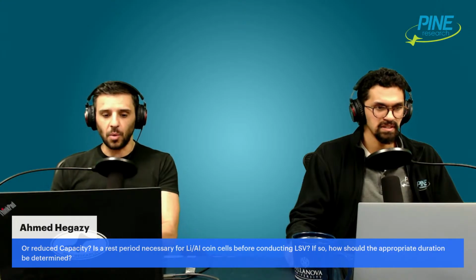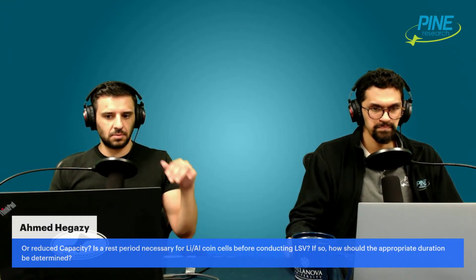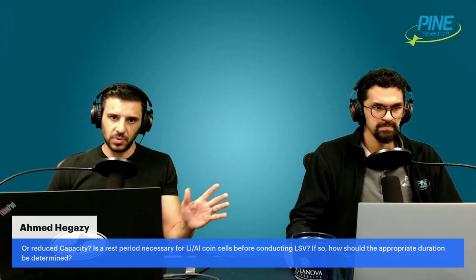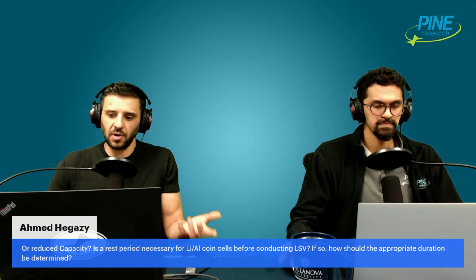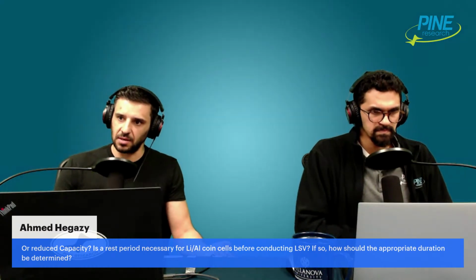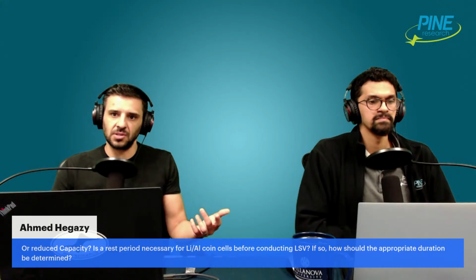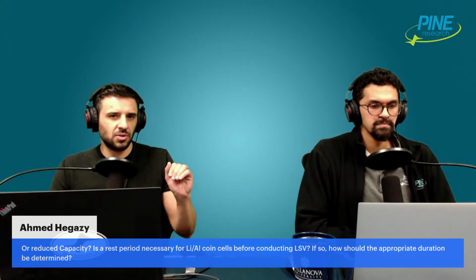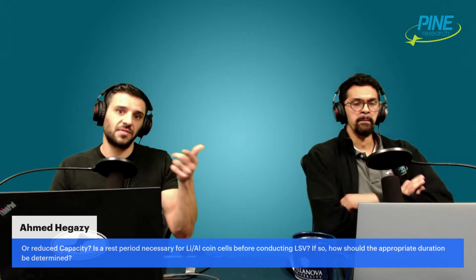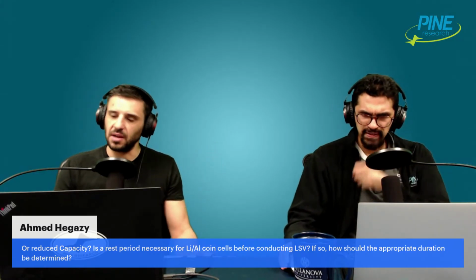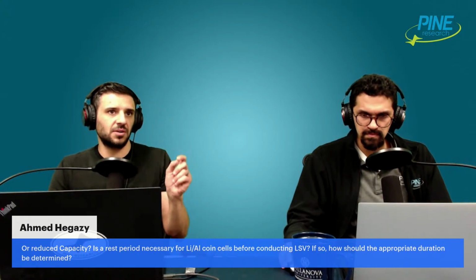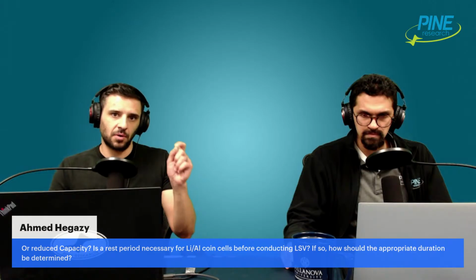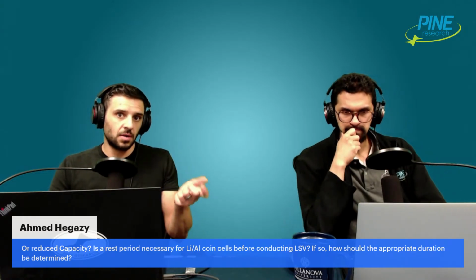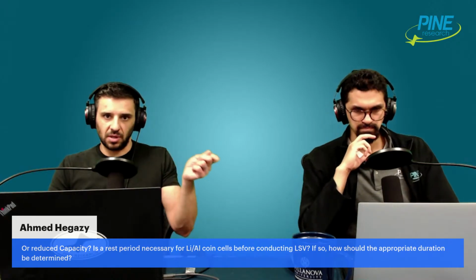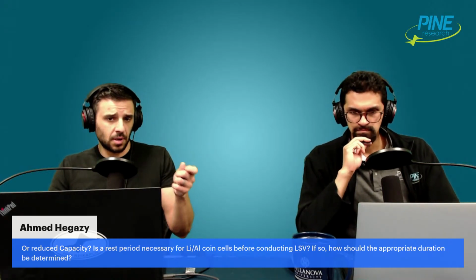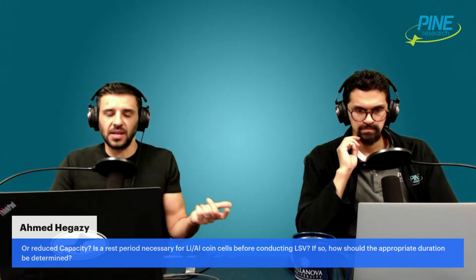So just connecting your system and trying to do CV at 20 millivolts per second, that isn't appropriate. That isn't how batteries work. However, if you're doing LSV at a very slow scan rate, 1 millivolt per second or slower, certainly it is something that is done pretty frequently, usually as the first step, as a diagnostic to check for those faradaic reactions, hence the first question, right? You're checking if you're testing a material that you think will work as a cathode or an anode, but you're not sure, because in theory it should intercalate or deintercalate or hold lithium, but you don't know. Theory guides, experiment decides, right?